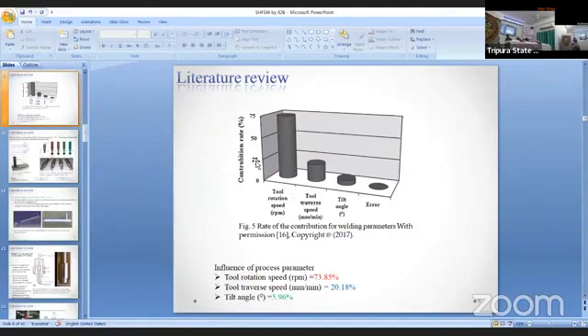So this shows the contribution rate versus the different welding parameters. You can see here that the tool rotation has got the most significant influence. So almost 73.85% contribution to welding. Then comes the contribution of tool traverse speed and then tilt angle, because the pin also is set at an angle when the welding is being done.